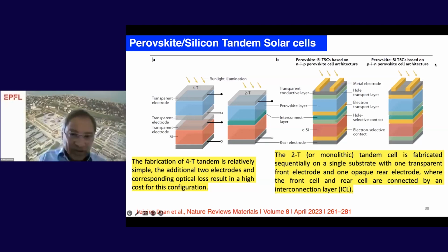The drawback of the two-terminal configuration is, as I mentioned before, the composition has to be mixed bromide and iodide. The different halides will have a segregation problem. Even the cations also segregate. So the cation has to be cesium, which is extremely stable, and pure iodide. This can be a very interesting composition for the two-terminal configuration. In order to avoid these complications of segregation, one approach will be the four-terminal, but in the four-terminal, you have to have two extra layers of electrodes, which is an extra cost.